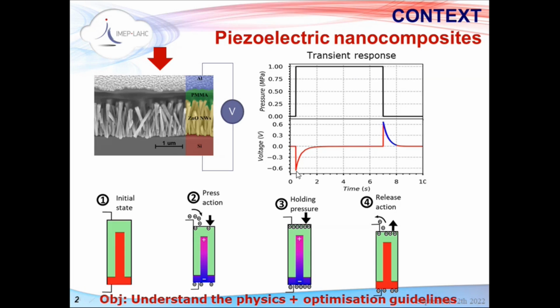So basically you measure this, and eventually because you have a positive and negative polarization here, all the charges in the metal, for instance, will flow and will try to compensate this polarization. So eventually this potential will decrease and it becomes zero if you leave this constant pressure. And then if you release the pressure from this device, as I represented here, then the polarization will disappear, and you will measure a peak of voltage, which is inverted, corresponding to the first peak. So this is classical, actually, for all materials, not only the composites.